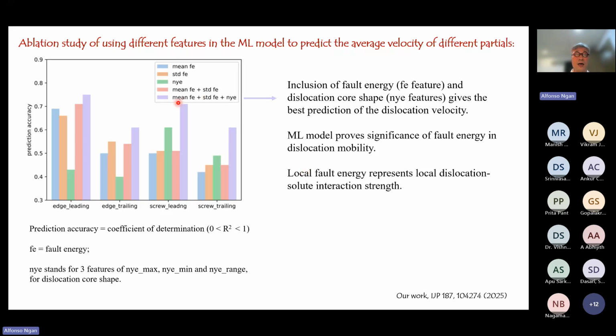So we found that it's actually this purple bar which is more dominating. So this is like an ablation study. We have a number of factors, and we knock out the factors one by one to see how well the machine learning model will predict the velocity. As you can see, the highest prediction accuracy comes from the factors where we have the fault energy as well as the core shape or core width of the dislocation. So both the fault energy and the Peierls barrier are controlling, which of course in hindsight is common sense, but we are able to prove that objectively from a lot of MD data.